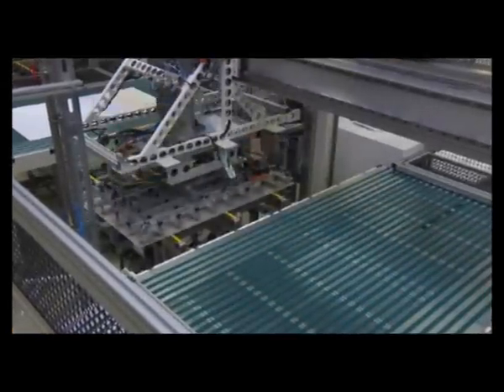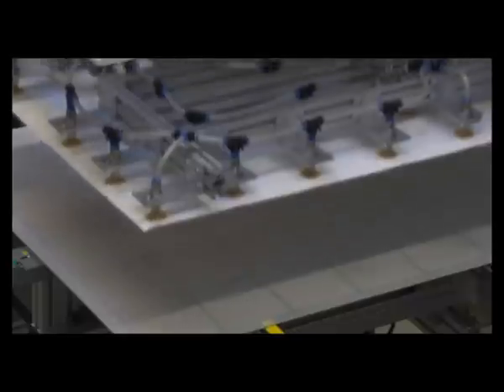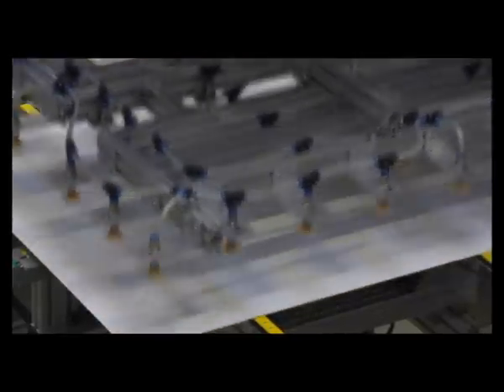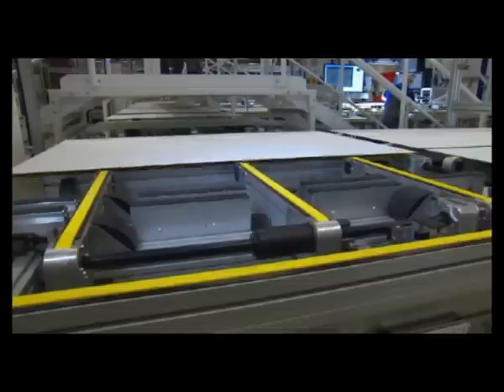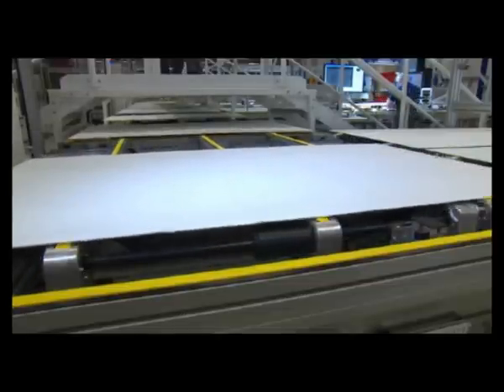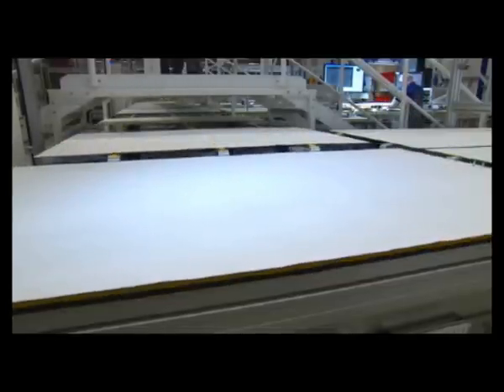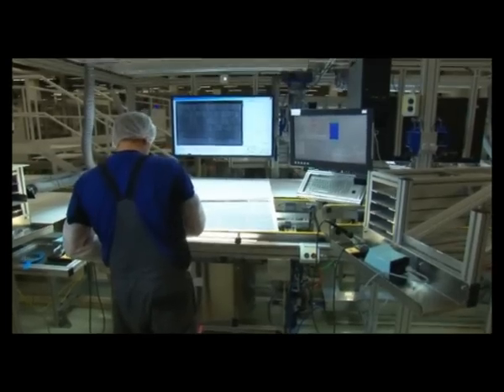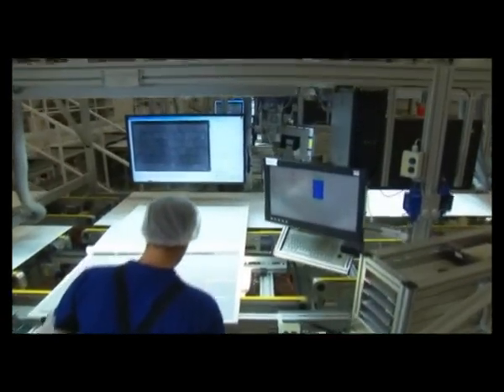It's given a second transparent EVA film and a very robust rear film that resists the system voltage of photovoltaic systems of up to 1000 volts without any problems. The complete package, experts call it a layup, is subjected to additional testing procedures. The electroluminescence measurement, for example, reveals possible hidden cell breakage. The trained eye of our module specialists also helps guarantee consistently high product quality.